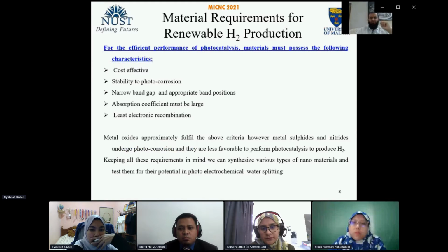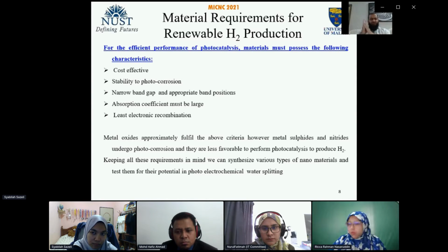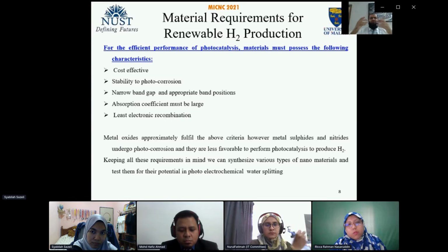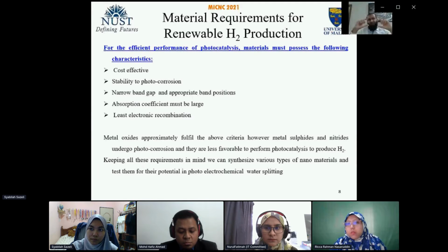So what are the requirements for a material to be photoactive or a photoelectrode? It must be cost effective. It must be stable towards photocorrosion. It means it shouldn't be depleting. The band gap should be narrow. For water splitting, we need an energy of 1.23 electron volt. In addition to that, with overpotential, it is normally 1.6 electron volt. And it is observed that if the band gap is in the range of 1.6 electron volt to 2.2 electron volt, then it can be an efficient material for water splitting.